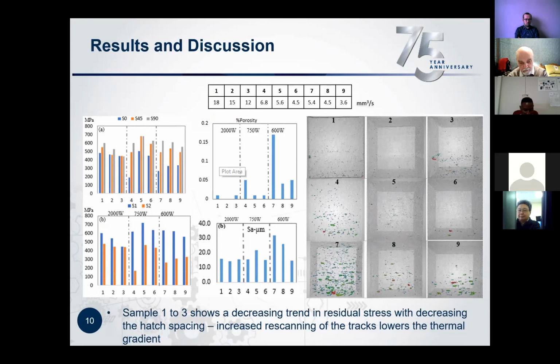And then another thing that we picked up was that sample 1 to 3 show a decreasing trend in residual stresses with decreasing hatch spacing. This can be interpreted as the effect of rescanning. So you can imagine if you reduce your overlap rate between the tracks, you are going to have a lot of remelting, and that will help in reducing your thermal gradients and ultimately reducing your thermal stresses in the part. So you can clearly see this with sample 1 to 3, because that's where we only varied the H spacing, and in the other samples we are varying the scanning speed.